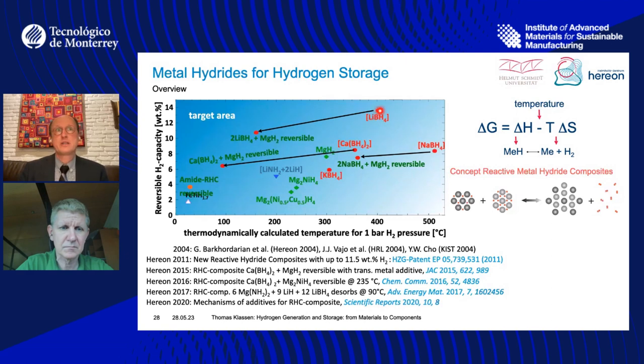So our idea then was, and this was about 2004, to combine two hydrides like magnesium hydride, lithium borohydride. And then you have part of the one hydride, the boron of the lithium borohydride, reacting with the magnesium of the magnesium hydride, and you form magnesium diboride, which is also a very stable compound. And this gives you some additional heat, or it reduces the overall reaction enthalpy to release hydrogen. So this is why you end up in the capacity somewhere between the two hydrides, but at much lower temperature.